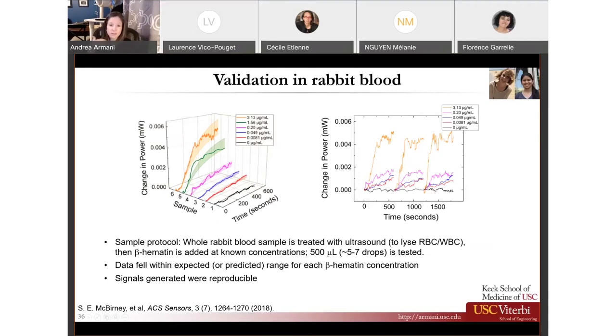And then we looked at reproducibility. In our system, the entire closed box system, we put our sample shaker on a motorized stage such that we could do a measurement, then shake the sample, do another measurement, and then shake the sample and do another measurement. We did multiple measurements and were able to get fairly reproducible data, which we felt was important because being able to reproduce and reanalyze the same sample multiple times gives you a certain amount of confidence in your actual measurement.